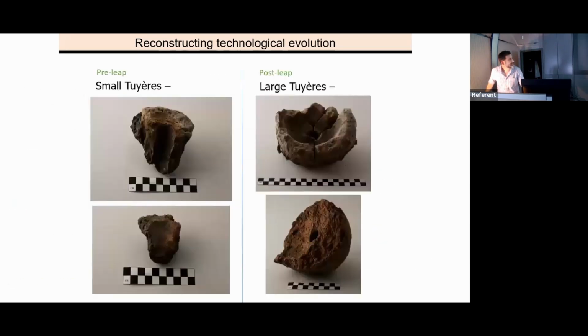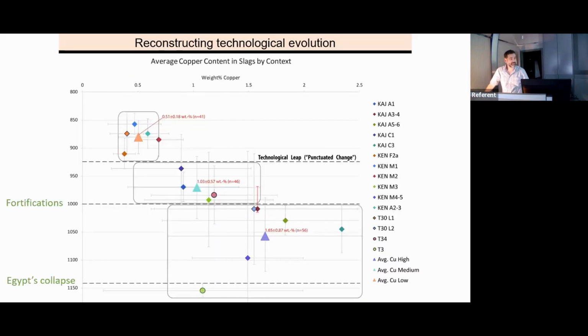But the point is that there is a major leap in the technology, and we can see it even in the installations themselves. Tuyeres are a sophisticated device made of clay, which connected the bellows to the furnace. It was the most important part of the installation because it protected the bellows, which were made out of organic material, from burning and getting destroyed. So there is a major change in the size of the tuyere and the size of the furnaces themselves. Okay, so there is a technological leap here, and the dating is very good.